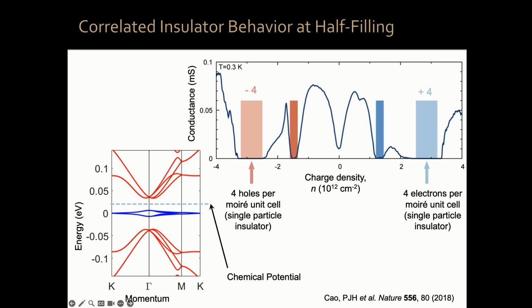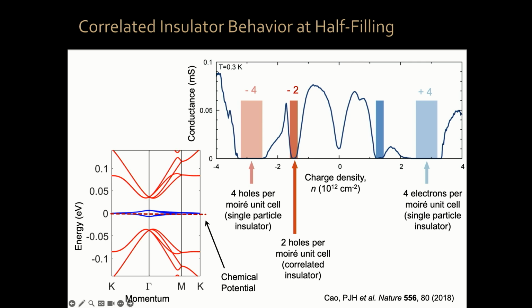The interesting thing happens when you put 2 holes per moiré unit cell. At 2 holes per moiré unit cell, your chemical potential is in the middle of a band. It's a band which is very flat. It has a very high density of states. There's tons of states for electrons to conduct. This should be a super highway for electrons and conduct super well. Yet, the conductivity is 0, okay? It's something that should not happen in single particle physics, but happens in many body physics. The interactions between the electrons lead to an insulating state when this should be a very good metallic conducting state.